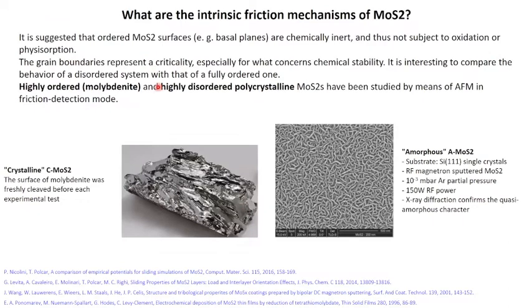Considering the results that we found at the macro scale, we wanted to deepen the aspects of the intrinsic friction mechanism. And in order to do that, we have to move to the nanoscale. So we measure, again, the tribological properties, but applying lower load and with smaller area of contact. So we use AFM. And in order to study the role of order and disorder of the coating, we select two different samples. One is the crystalline MoS2, so the mineral molybdenite, and the other one is a quasi-amorphous MoS2, so our polycrystalline coating.